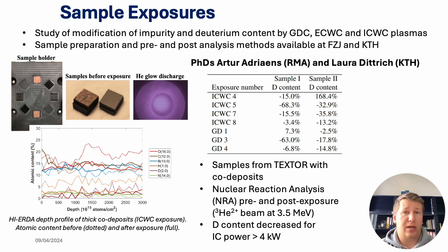We exposed samples made of graphite wall panels of the TEXTOR tokamak to glow discharge cleaning plasma and to ion cyclotron wall conditioning plasmas. What we found is that a change in the plasma parameters increases the removal rates of species from the co-deposits on the samples. This also allows us to show how the concentration of trapped deuterium changes after exposure to the wall conditioning plasma at different input powers and with different working gases.